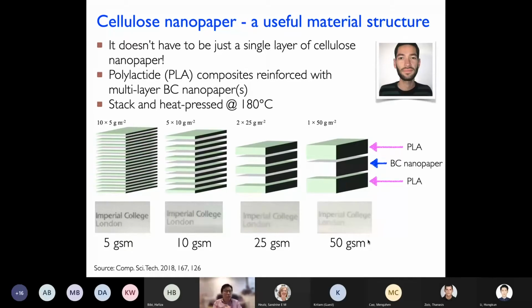So that's the thesis of Martin here. What he did was to have nanopaper of different grammages. So this one would be a piece of nanopaper that is 50 grams per square meter. So areal density or grammage, essentially a measure of how much mass of cellulose per unit area. Or you can actually make the papers in such a way that it is 25 grams per square meter, and you put two of them together, so the overall cellulose content within a composite is still 50.